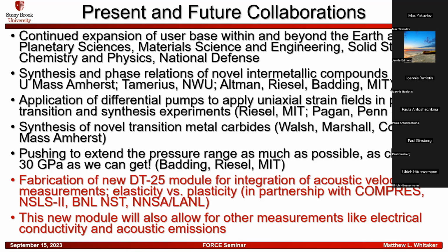We're continuing our work on novel transition metal carbides and pushing to extend the pressure range that we get in the press as much as possible. It's close to 30 GPa as we can get.